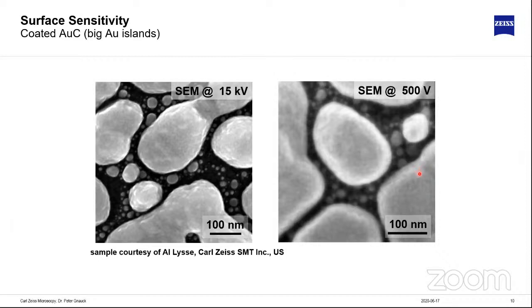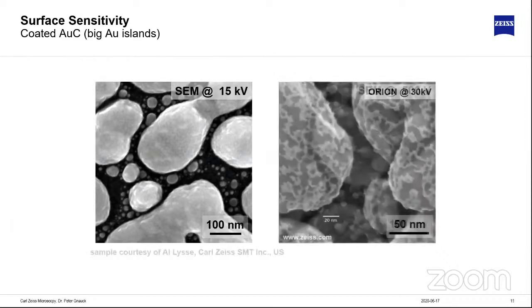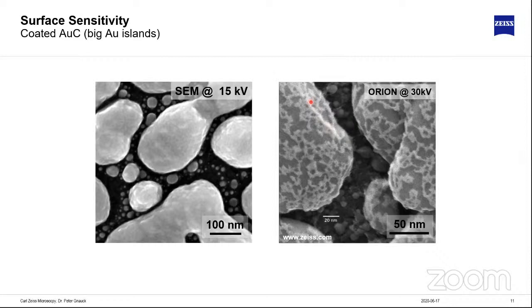If we're imaging exactly the same in the helium ion microscope, we receive this image here. We have razor sharp edges. We can see the surface contamination, the carbon, razor sharp on the gold grains. This is twice the magnification than this image here. And that means in the helium ion microscope, we do not sacrifice resolution for surface sensitivity. So we always have the full resolution at the surface at all times.